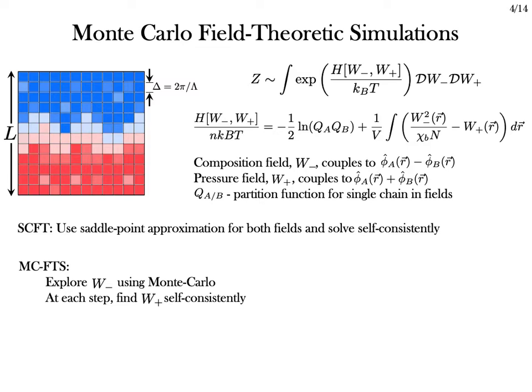There are other, less approximate ways of approximating the integrals. One can, for example, expand the exponential to Gaussian order, adding a fluctuation correction to mean field theory. Another notable example is renormalized one-loop theory, which expands the integral into a set of integrals given by Feynman diagrams and, as the name suggests, expands up to one loop. We use a numerical approach to evaluate the integrals, field-theoretic simulations.